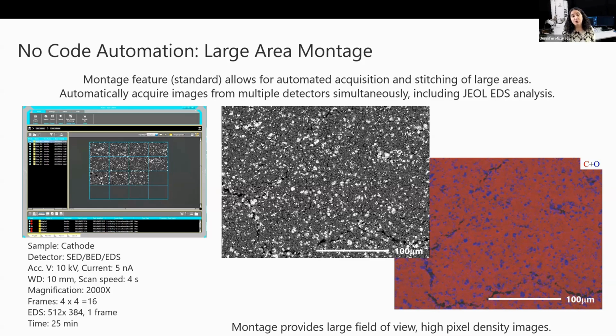This example shows a 4x4 montage of that cathode material taken with our ultra-high resolution SEM. The complete montage, including backscattered and secondary electron imaging along with the EDS map analysis, was acquired in approximately 25 minutes.